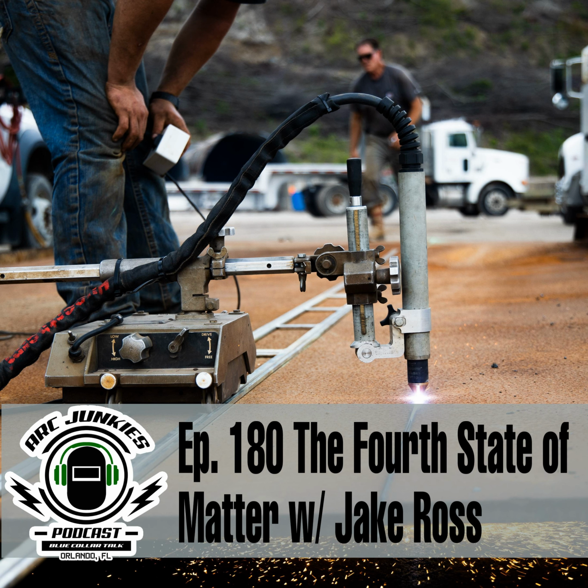Yeah, so a good rule of thumb, and there's a little bit more to it, is that for PowerMax consumables specifically, you run the amperage process towards the thicker range of material. So 45 up to a quarter inch, 65 up to a half inch.